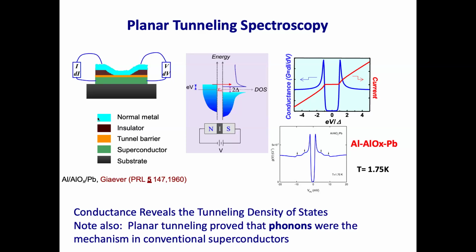So in case you see two peaks, why is that? Typically, you saw this associated with a gap, right? But then you have two gaps, so in this case, what are the kinks? These are phonons. I know, but typically it's just a mode electron coupling, right? Exactly, but why do you have two? Because lead just happens to have a 6 and an 8 millivolt phonon mode. Yeah, there's two phonon modes, so these aren't superconducting gaps, these are just the phonon modes. Okay.